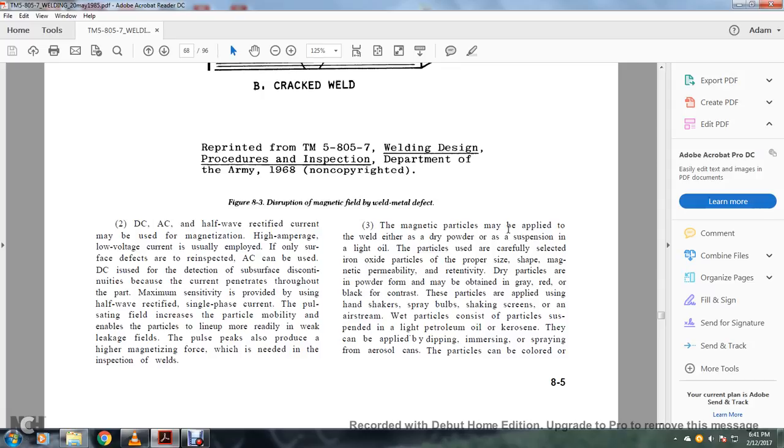3. Magnetic particles may be applied to the weld either as dry powder or in a suspension of light oil. The particles are carefully selected iron oxide particles with the proper size and shape, and high permeability and low retentivity. The dry powder form may be obtained in gray, red, and black contrast particles, applied with hand shakers, spray bulbs, shaking screens, and an air stream. In the wet method, the particles are suspended in light petroleum oil or kerosene. They can be applied by dipping, immersing, and spraying from aerosol cans.